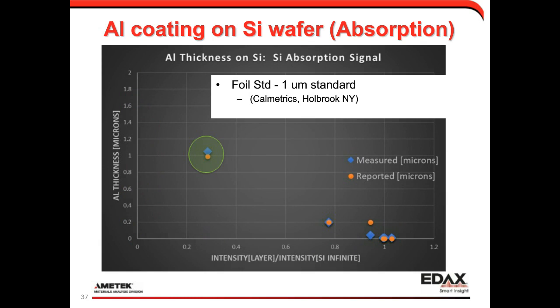This is the value that we get off of a 1 micron standard. Our accuracy in this case, calibrating off of a bare silicon wafer, is about 5%. That's pretty good for just putting in an infinite element, calibrating, and getting a measured value for a 1 micron foil.